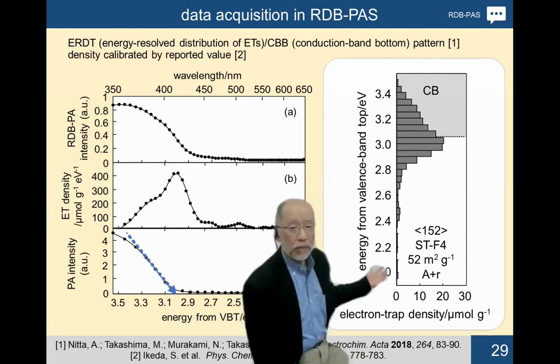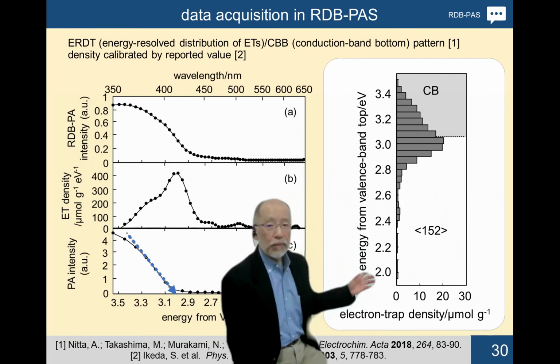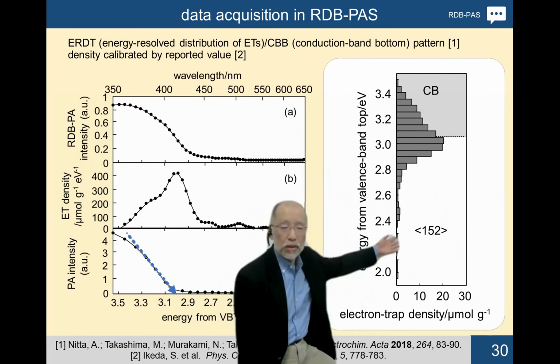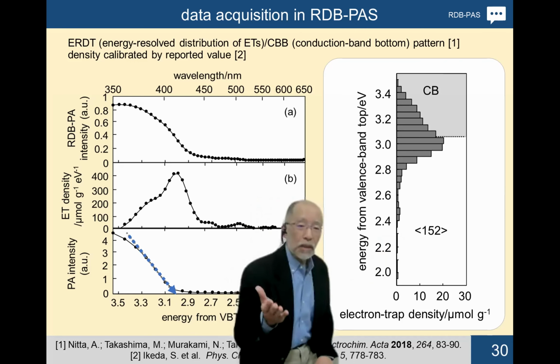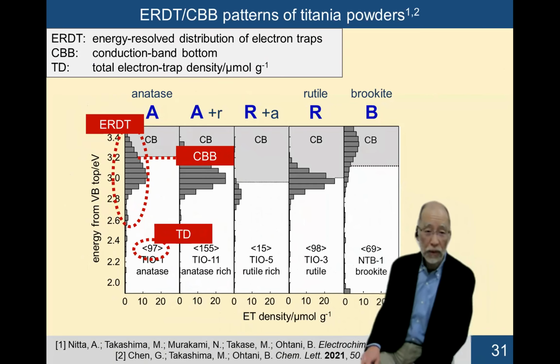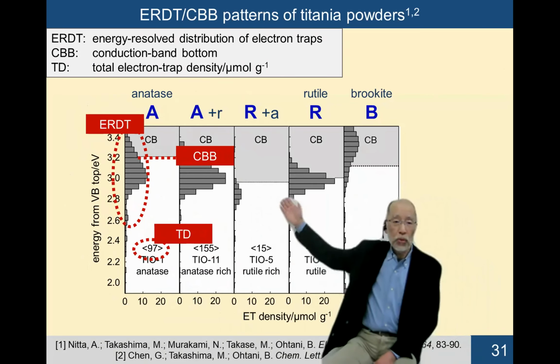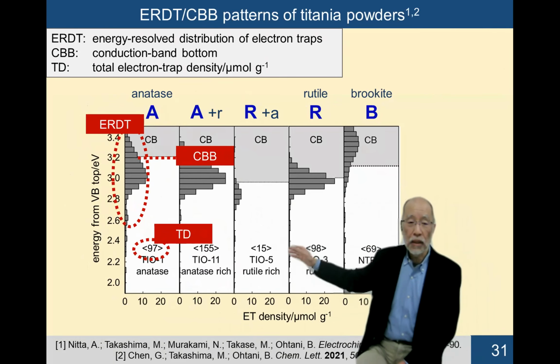And this is a commercial titanium oxide sample. It has a specific surface area of 52 and is annotated as containing a small amount of rutile. But without using this data, and 152, this is the total density. By using this ERDT pattern alone, this titanium oxide can be identified. And this is a representative commercial titanium oxide sample, where A annotates anatase, R rutile and B brookite. And the ERDT-CBB pattern is really different depending on the bulk crystalline structure.